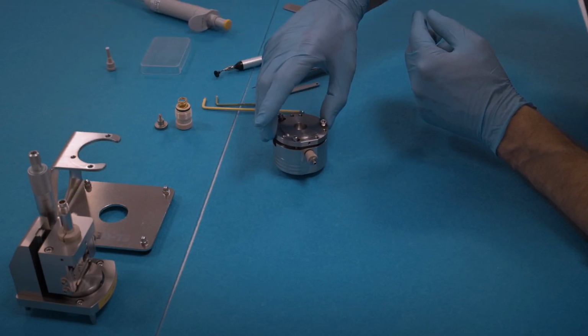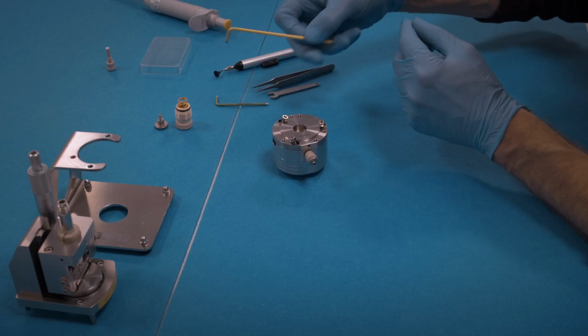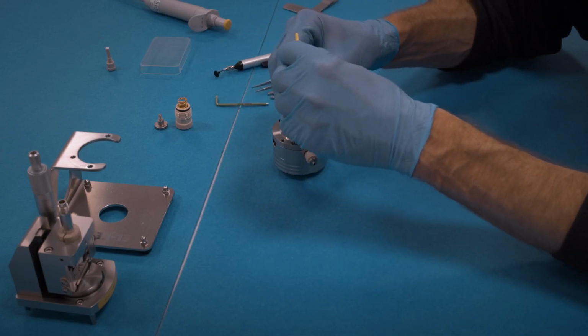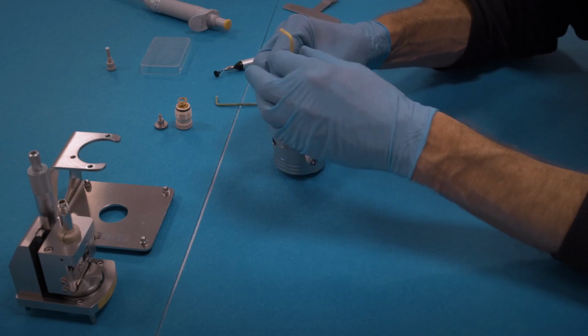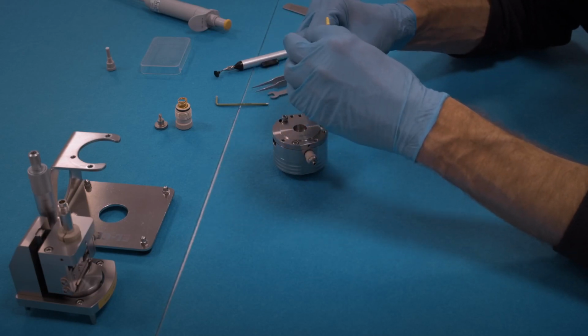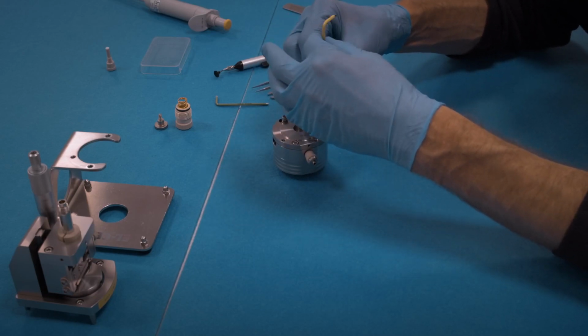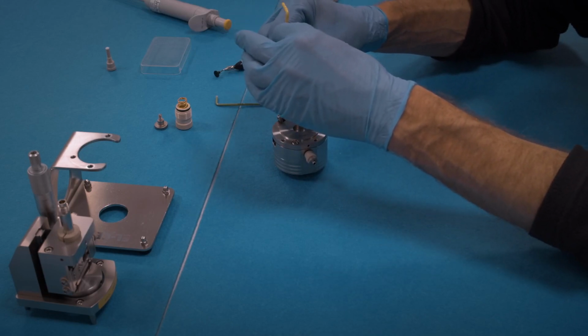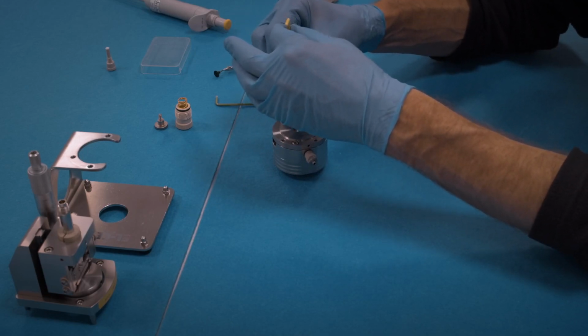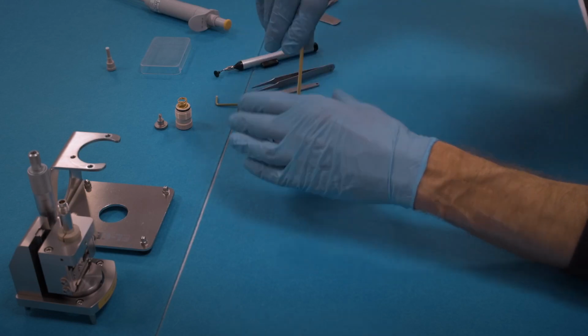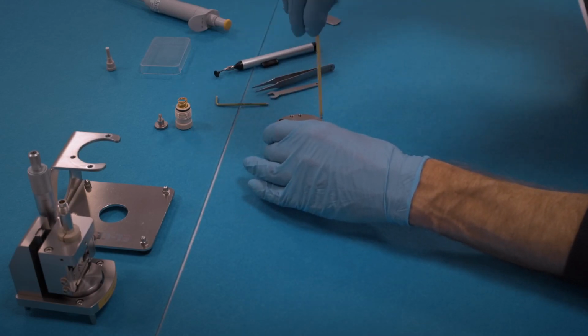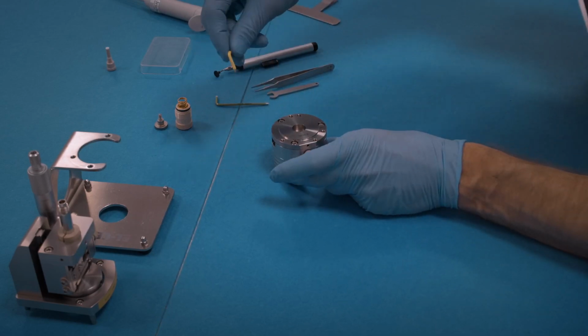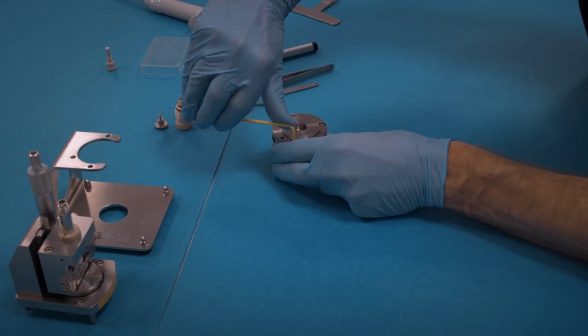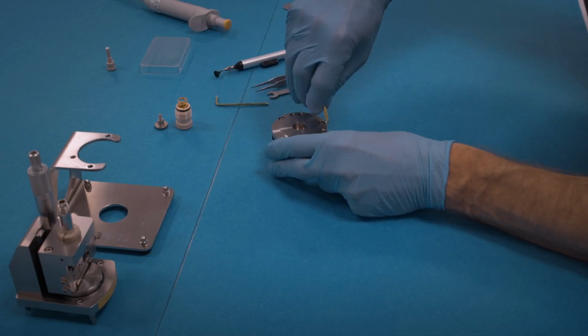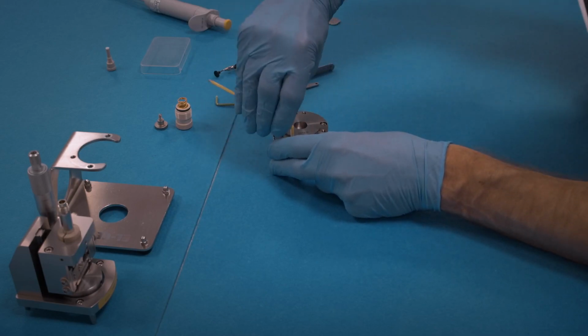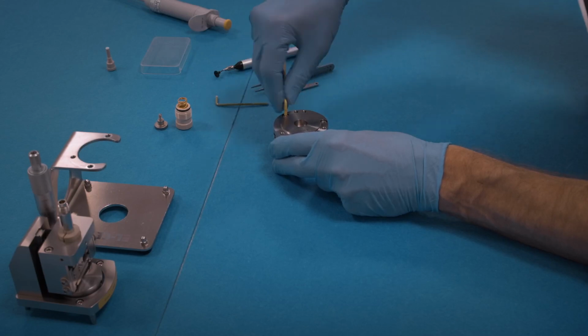Then attach the cover flange and tighten the screws. The PTFE seal used to seal the metal foil is significantly thicker than with a previous version of the dilatometer. And so you have to apply significant force here in order to compress and tighten the cell.